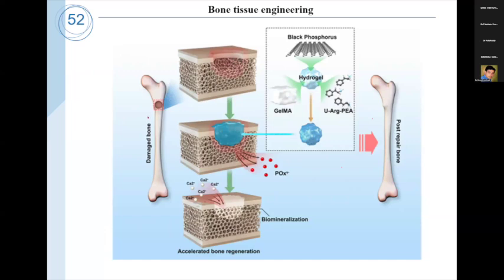So you see here the damaged bone. It is a bone structure with a defect site. When we implant a hydrogel-type material filled with black phosphorus, it could initially involve biomineralization to form hydroxyapatite structures on the surface of the hydrogel structure. Once hydroxyapatite forms on the surface of the hydrogel, it easily bonds to the surrounding native tissue, so that the surrounding blood vessels easily penetrate into the hydrogel structure. Then the bone structure starts to grow to repair the bone defect site.